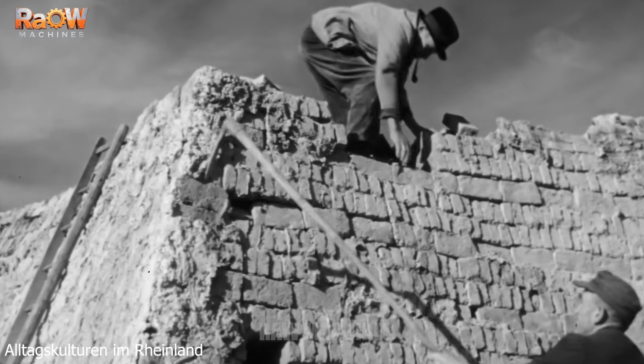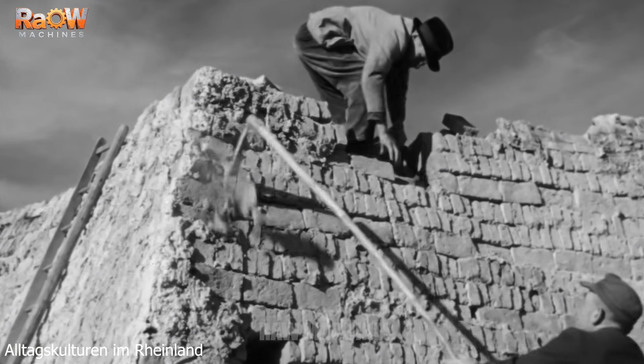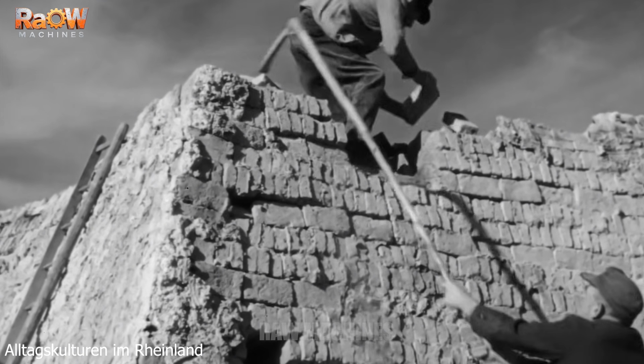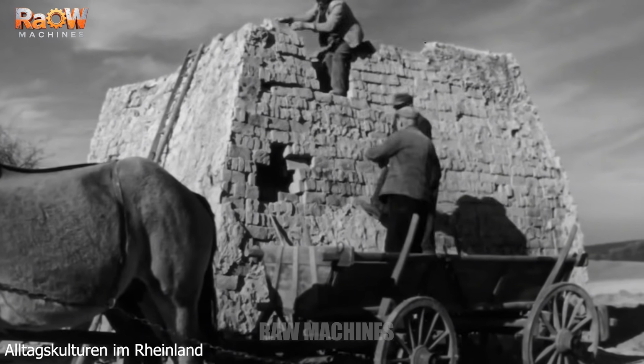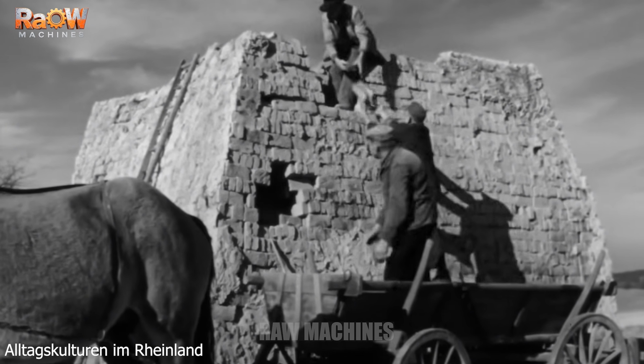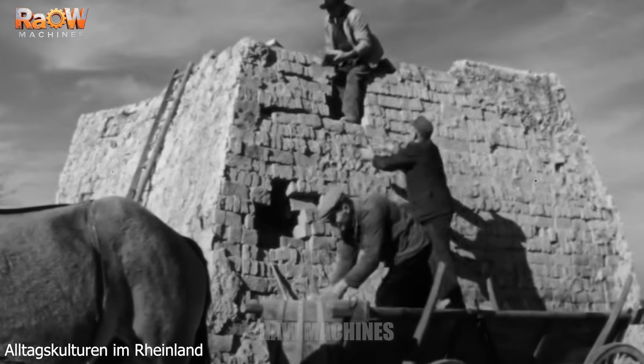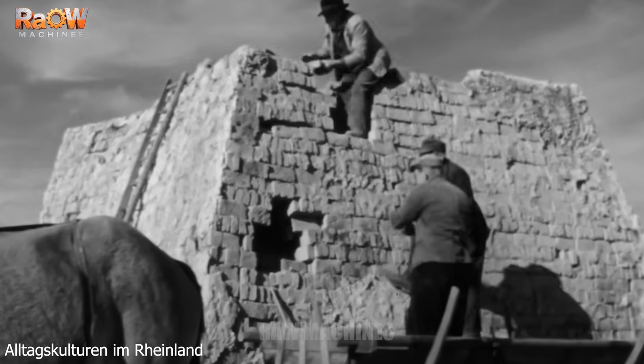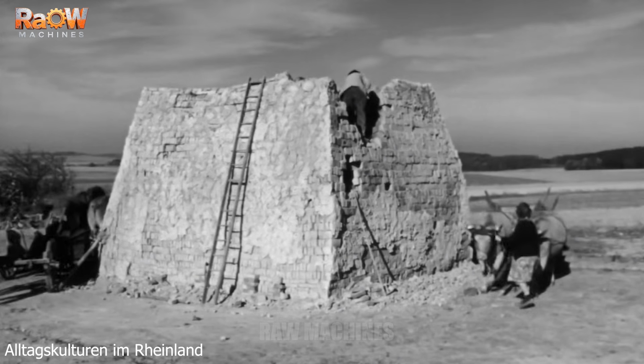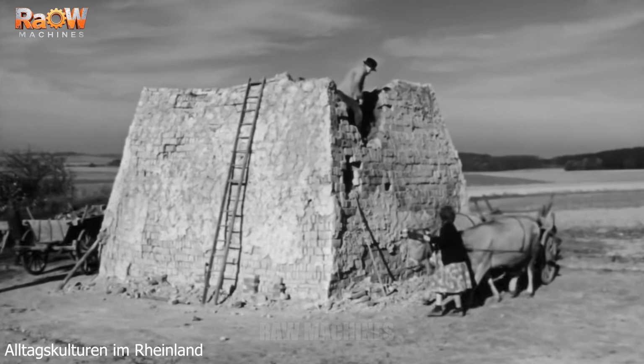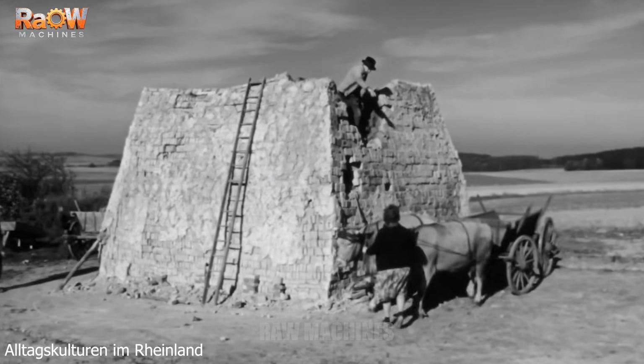The master burner tested the results by removing bricks from the inner courses. Bricks of good quality showed a reddish-brown color and produced a clear ringing sound when struck together, indicating that they were fully fired. A familiar sign of a successful firing was the kiln crown settling into a shallow, bowl-like depression.